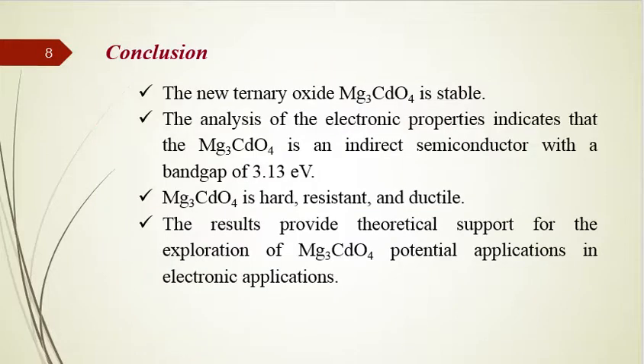To summarize, the structural stability of a new identified oxide is calculated by means of density functional theory. The analysis of the electronic properties indicates that the ternary oxide is an indirect semiconductor with a band gap of 3.13 eV. Moreover, it is hard, resistant, and ductile. The results provide theoretical support for the exploration of new material potential applications in electronic technologies. Thank you for your attention.